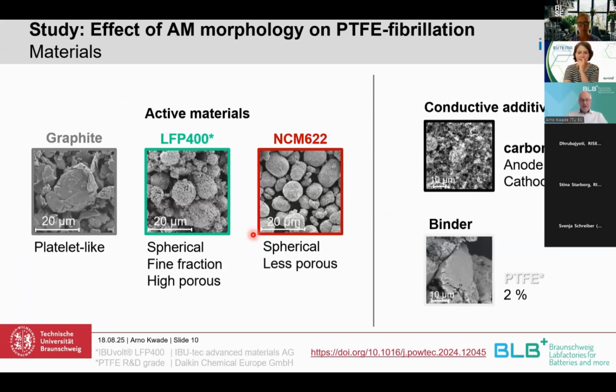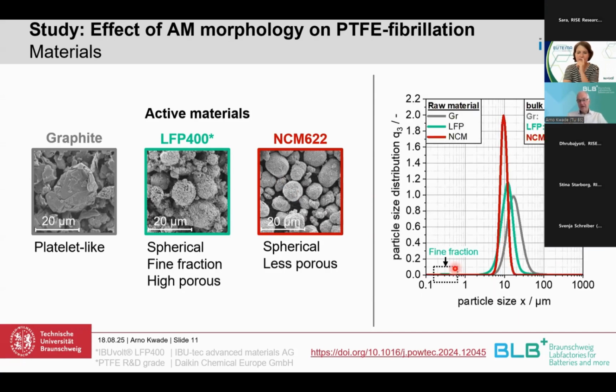In this presentation, I thought it might be interesting to use a study which we also already published on how the different active material, let's say, influence the dry coating process. That is graphite, LFP as a, let's say, low-cost cathode material, and NCM as a more high-cost, high-performance active material. And in all formulations, we had some carbon black. So on the anode side, 1.5%, on the cathode side, 3%, and we have almost always 2% of binder PTFE.